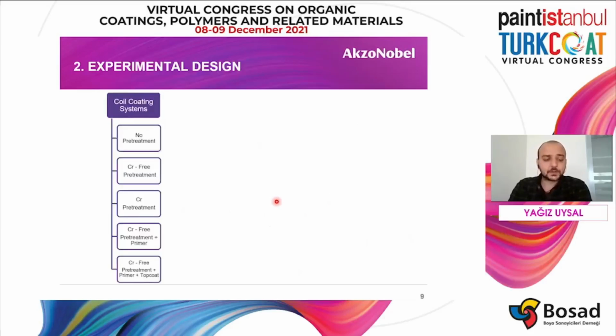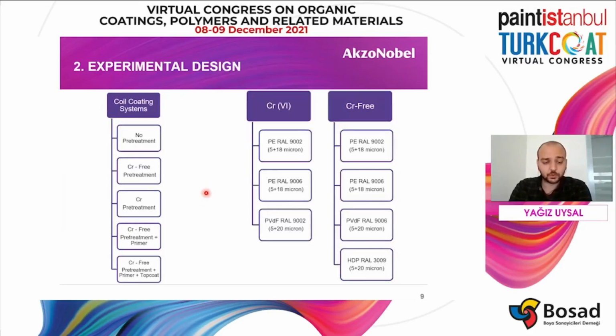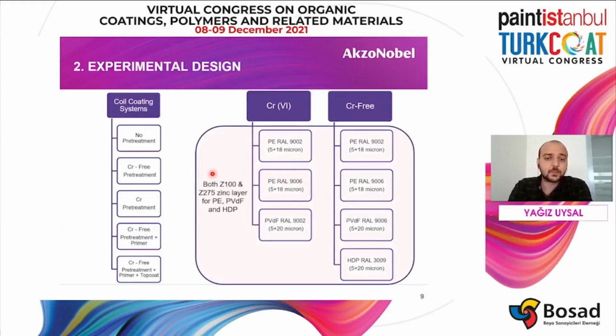And this is our sample set. Firstly, we will look at the coil coating layer comparison in the electrochemical impedance spectroscopy, and then we will move on to top coats. We had three kinds of top coats: polyester, PVDF, and high durable polyester. We also have two different zinc layer amounts, Z100 and Z275, for all these different top coats.